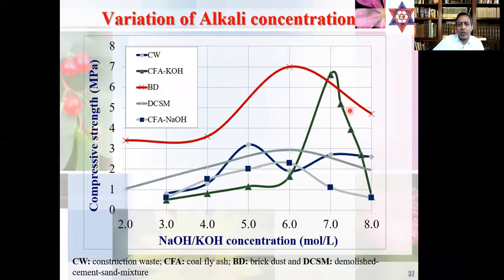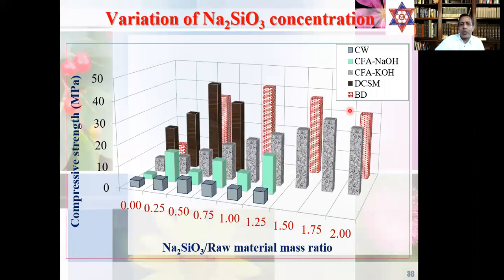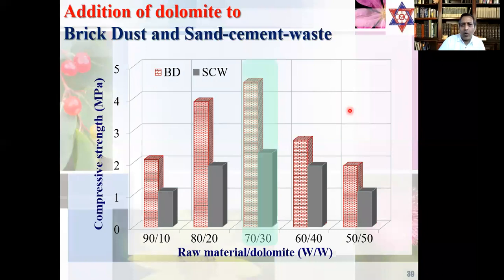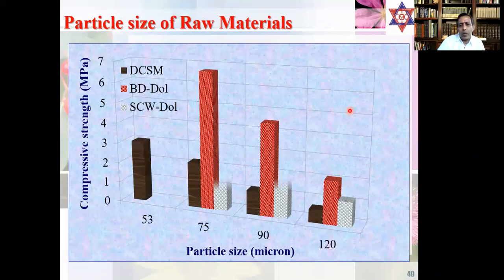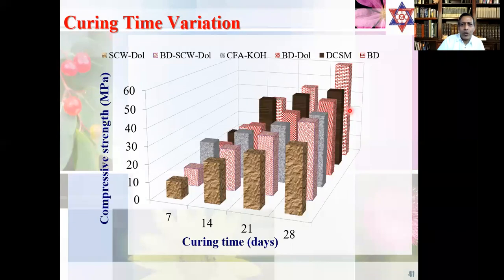There is another variation, alkali concentration. This is optimizing conditions I did. You'll see here the variation with sodium silicate to raw material mass ratio. There are a lot of variations. This is all chemical terms, I'm not going to give a lot of time on this. With the particle size variations, we get this. This is the curing time variation, and these are the real geopolymeric samples.